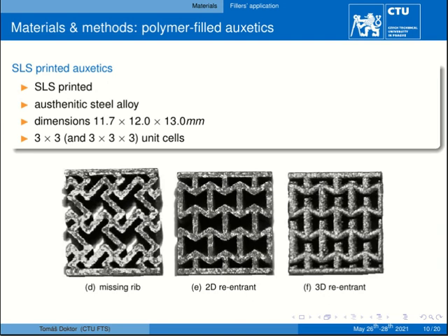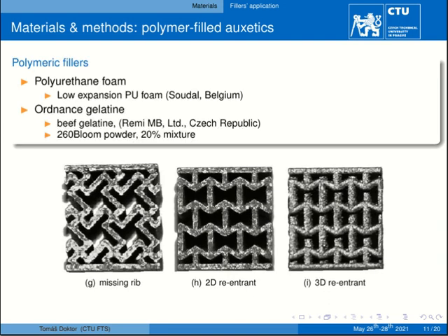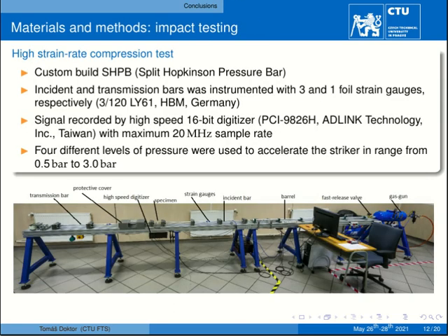without being at the contact phase. Two types of polymeric fillers were used: low expansion polyurethane foam and ordnance gelatin. The samples were tested in quasi-static conditions and under high strain rate conditions using a split Hopkinson pressure bar apparatus, which is located at the Czech Technical University in Prague in the laboratory of high strain rate phenomena.